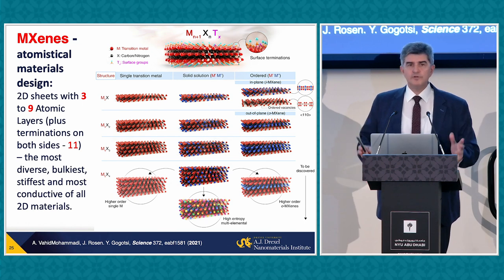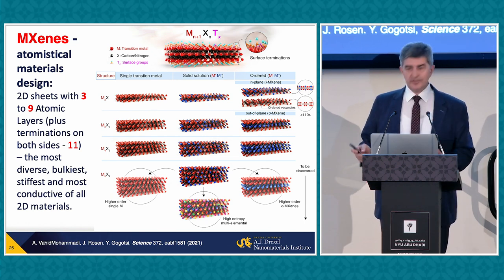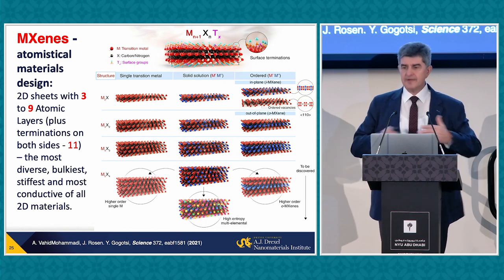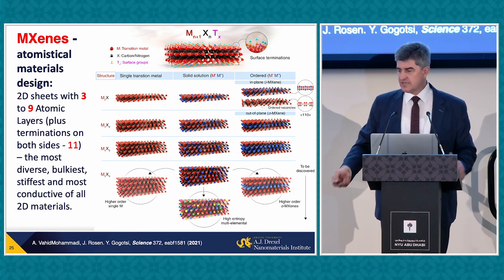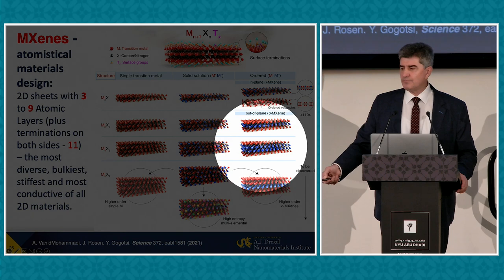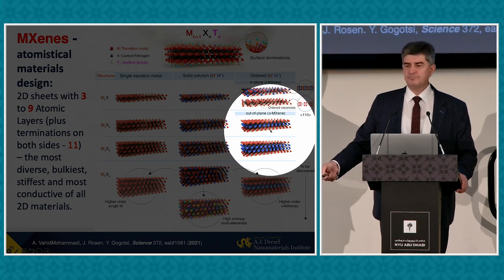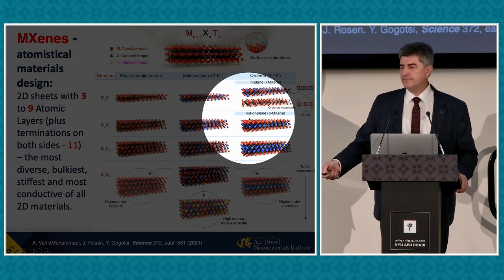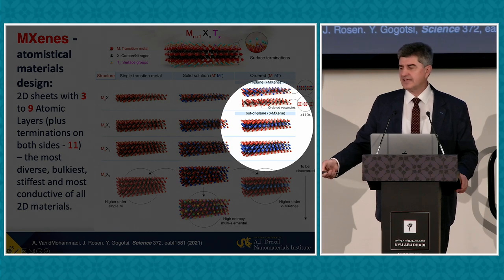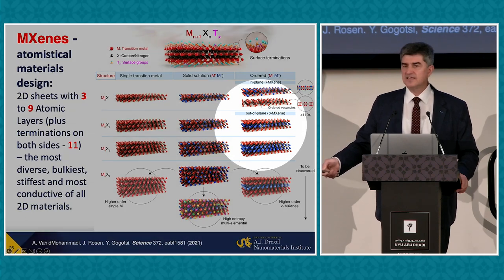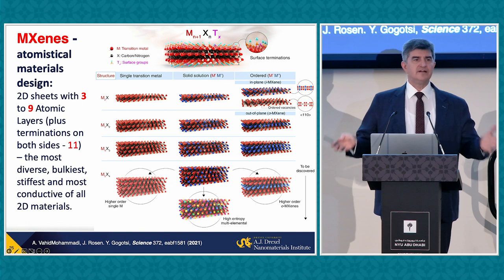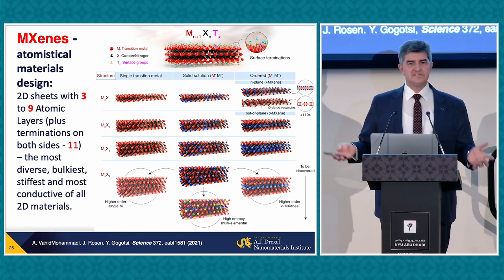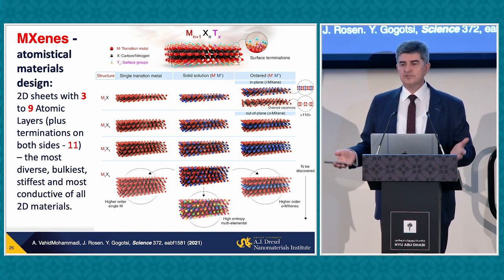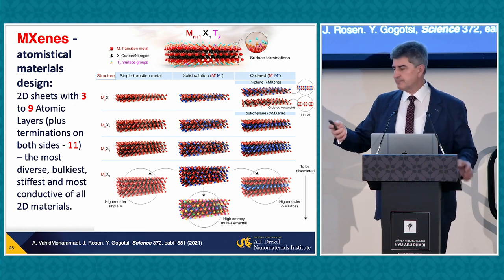But we're also pushing atomistic design of materials. We can make not just simple structures. We can make materials which are atomic sandwiches, like out-of-plane ordered MXenes, as we call them, with one element, for example, moly or chromium, being on the surface, another element making the inner layer. The element in the outer layer controls catalytic, chemical, and electrochemical properties. The metal in the inner layer controls electron transport, for example.